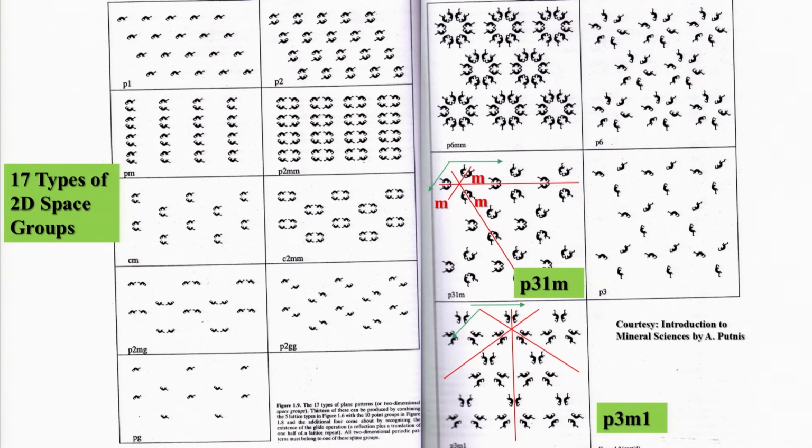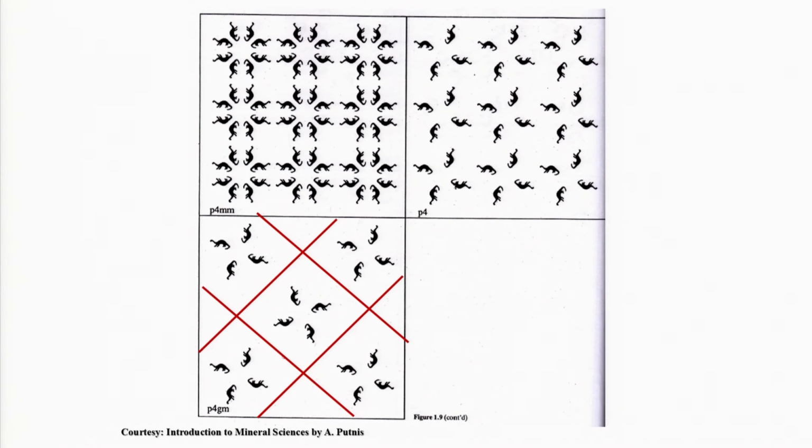We have the square lattices now. So, we have here the simple one, P 4 mm. You can immediately find out this is the position of the vertical 4-fold axis, and this is one plane of symmetry here, another plane is of this orientation. You can also think of another set of mirror planes of this orientation and another set of this orientation. So, this mirror plane and this mirror plane are at an angle of 45 degrees.